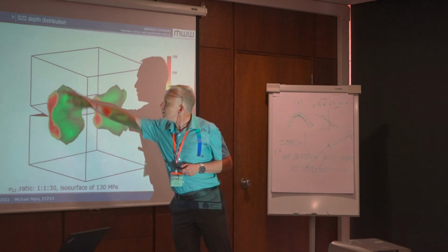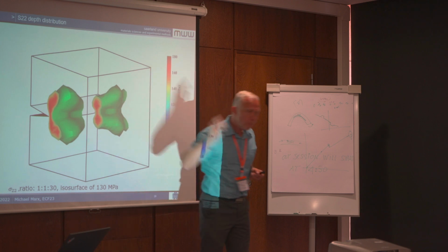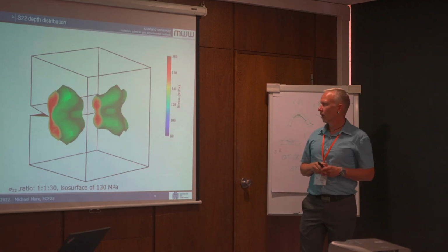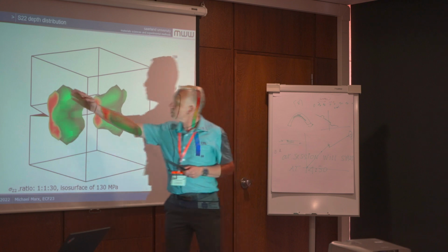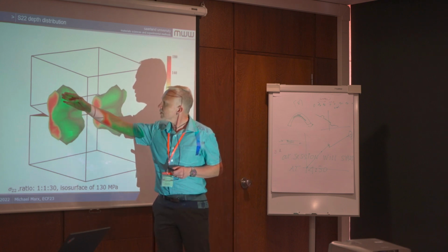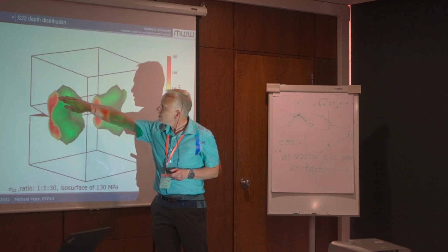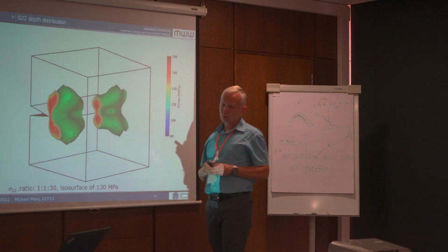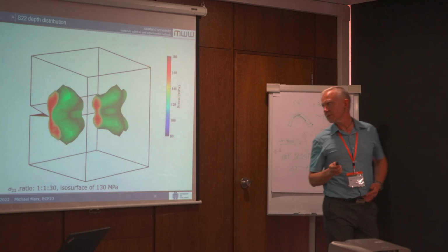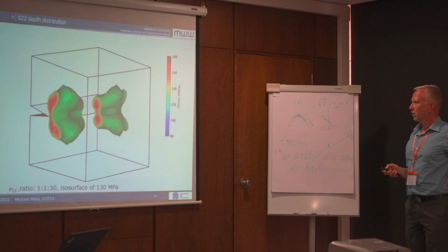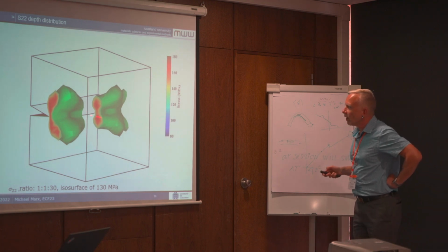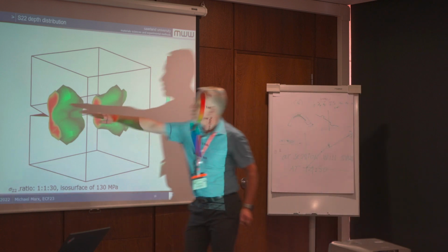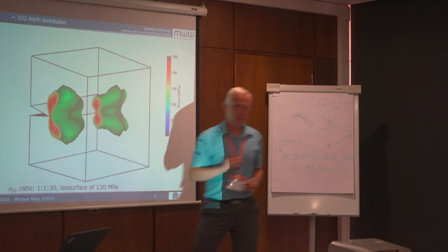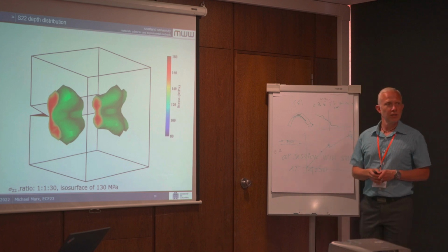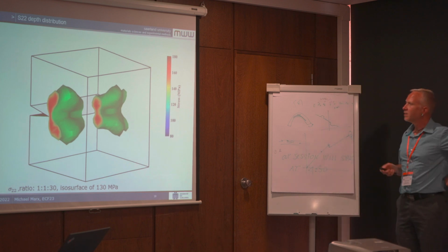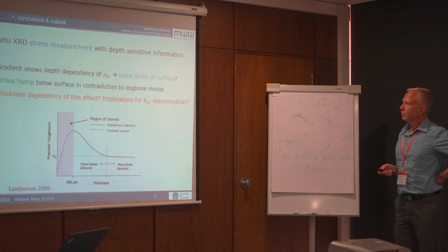And what you can see here is the hump I described at the beginning. So we have a reduced plastic zone stress field at the surface, then it increases, and then it decreases to the plane stress condition. This is what we got. It looks more or less symmetrical because we measured this part here, and the rest is only mirrored to get an idea how it looks in 3D.